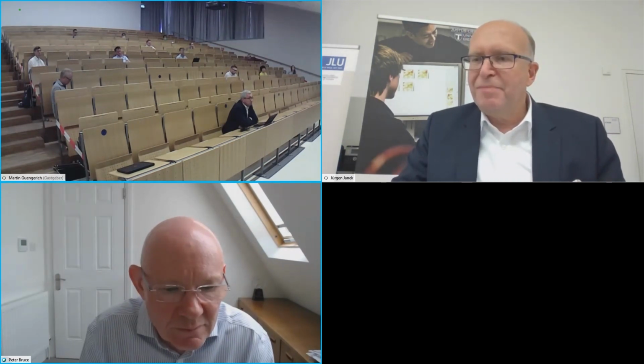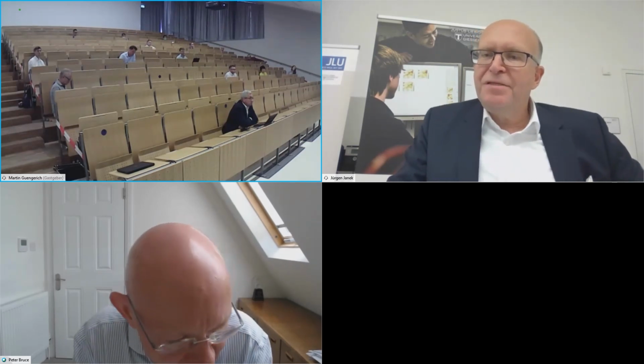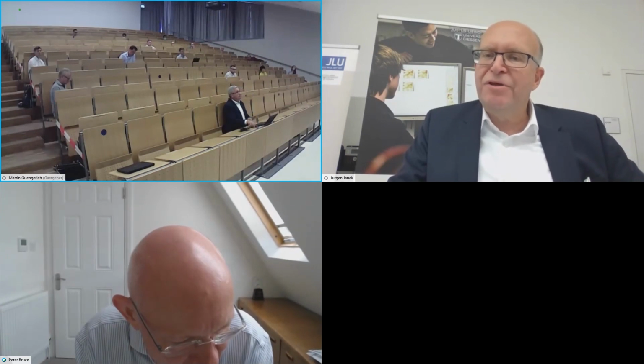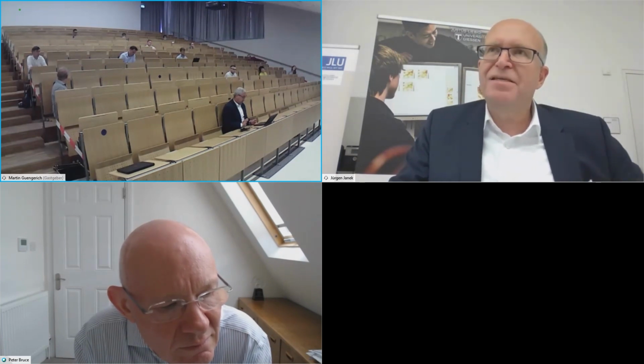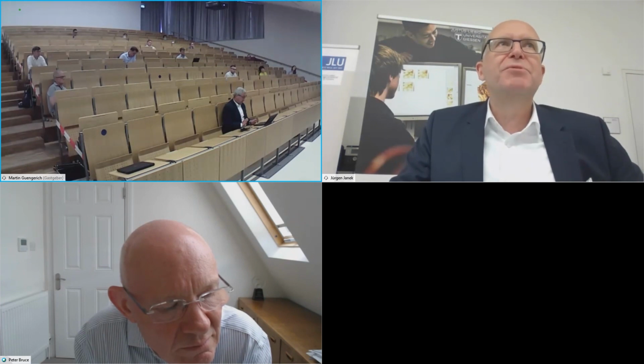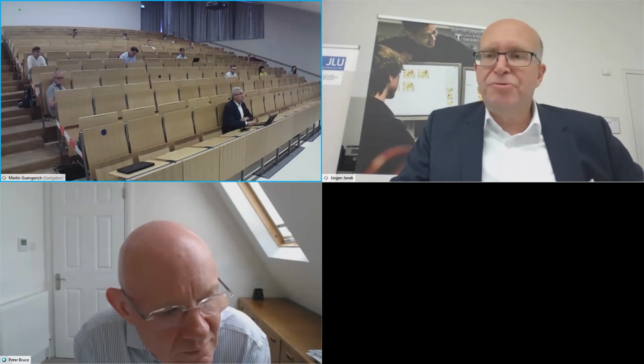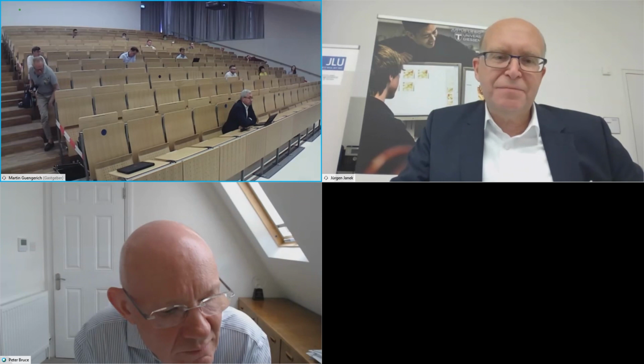Okay, so I have a question from our virtual audience, from Bernd Marcy, professor in inorganic and physical chemistry, and an expert for nanostructured materials. He says, in the first part, the XRD data show that the material in the charged state appears to be quite amorphous, at least XRD amorphous. And he asks whether this isn't really a problem for discussing what is going on in the material, because you seem to lose the long distance symmetry by amorphization. Is that the case?